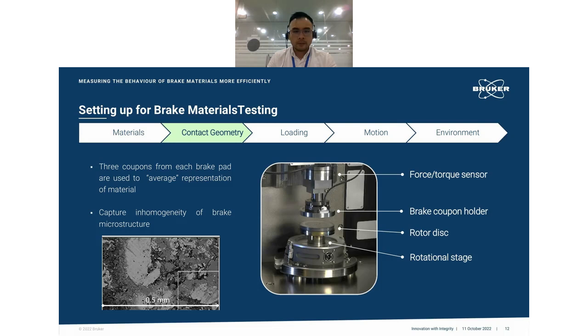In terms of contact geometry, like we've described in the earlier slides, we use three coupons from each brake pad to give an average representation of the material. One of the purposes is, of course, to capture the inhomogeneity of the brake microstructure from a huge piece to a small piece. So the brake pads are mounted on the brake coupon holder, as you can see in the image on the right, and it's going to be driven by a servo motor to press it against a rotating rotor disc.